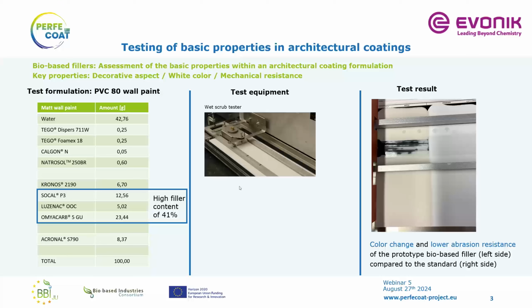And so here I'm showing you a picture in the middle of the equipment we use for the wet scrub resistance. So basically, it's a brush that will rub back and forth on top of the surface of the applied coating. And on the right side, you can see next to each other on the white, as you can see also immediately the color shift, a light color shift that you obtain when having the bio-based filler in the formulation compared to the standard on the right.